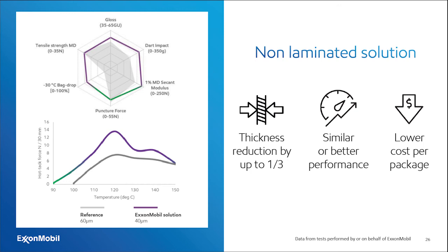The graph below is, in fact, the sealing performance. So the gray area and the gray line, that is the reference. In this case, it's a market reference of 60 micron thickness. So it's a little bit thicker than the average of 55 microns that Amelie just presented. From the graphs, you just see that the axes are made in such a way that you want to cover as large an area as possible. So larger area is better. So you can see that even when we compare a 40 micron ExxonMobil solution based on Exceed XP and Enable, we have similar or better performance. And on the bottom graph, it is shown sealability. So how fast it seals in your packaging lines, and a curve higher is better. So you see sealability is also better than the market reference.